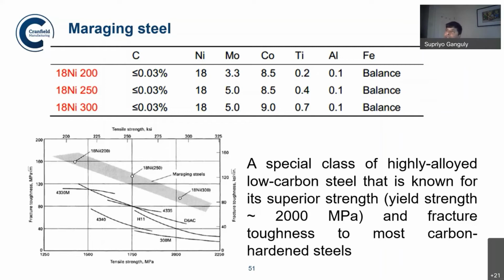When this maraging steel is formed, at normal cooling it generates martensite, and the strength is quite low actually. Then when it ages, it forms precipitates like Ni3Mo or something, and that gives the strength. This material can generate a tremendous amount of strength, and because of the nature of the precipitates, it generates quite isotropic strength. I mean, the strength is not dependent on the direction or anything, because the precipitates are quite spherical in nature, I would say.